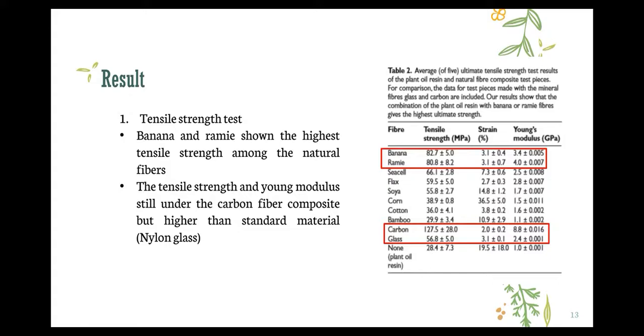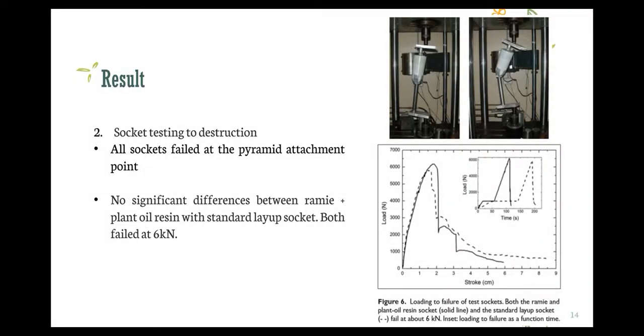For the result, first the tensile strength test. The banana and ramie show the highest tensile stress among the natural fibers, and the tensile strength and Young's modulus are still under the carbon fiber composites but higher than the standard material, which is the nylon glass. And then in the socket testing to destruction, all the sockets failed at the pyramidal attachment point, on the distal one.